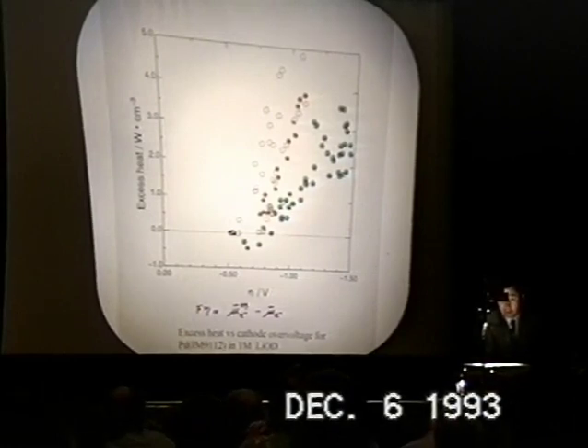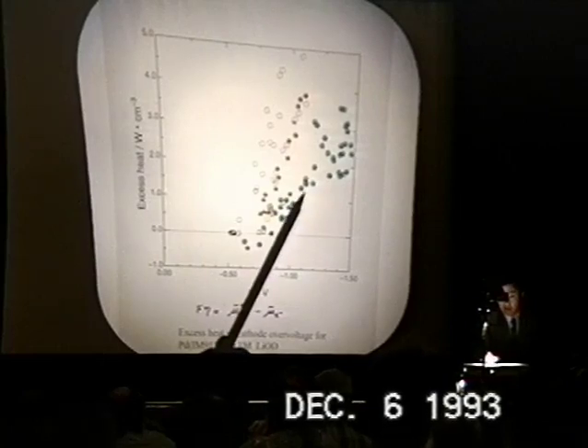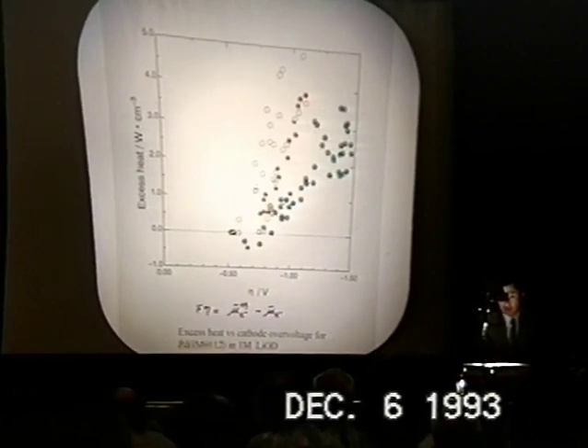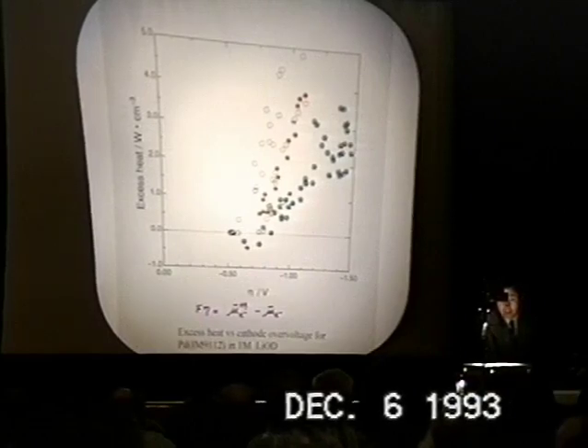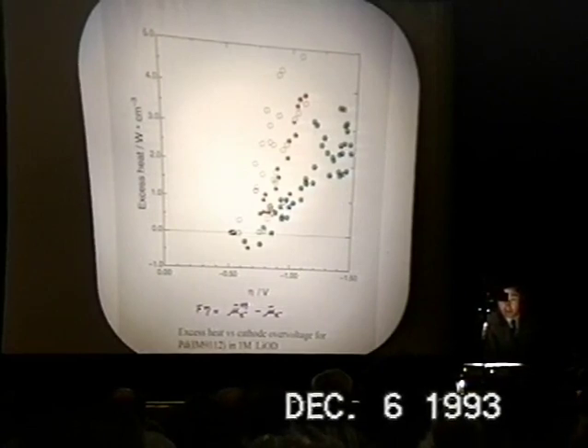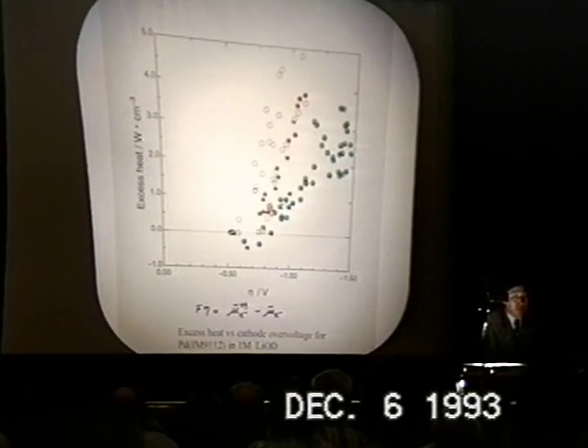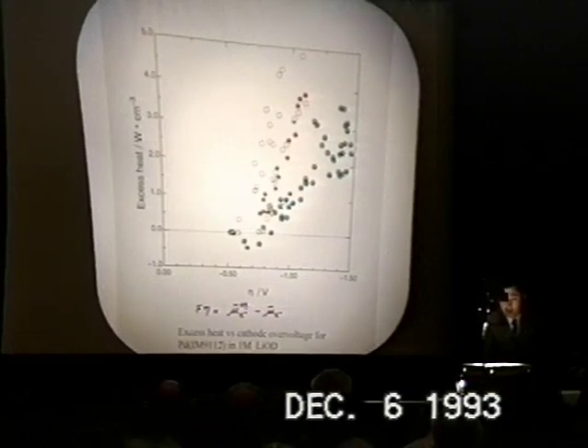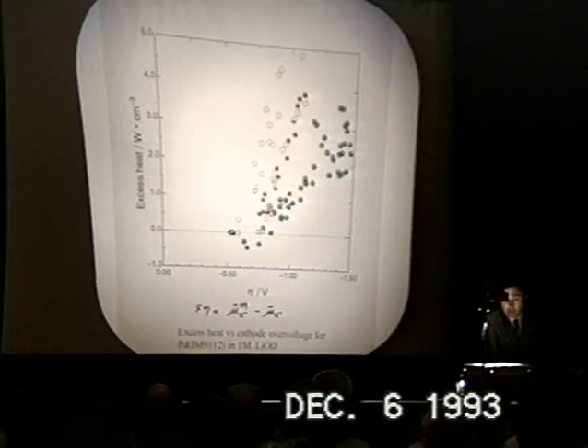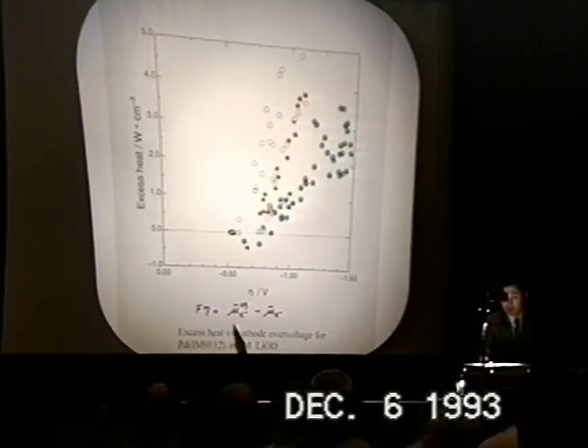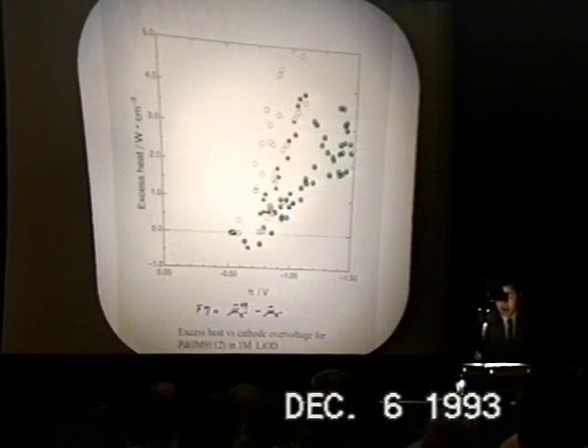But if we look at those data closely, those green data and red one and white one are well separated, and it looks as if they are well on the straight lines. The reason why we thought about plotting the data as a function of overvoltage is as a function of current density. The current density has nothing to do with the performance of the actual characteristics of palladium cathode. Only cathode overvoltage can give us the potential drop across the palladium solution interface, and also, as I have written down, we know the change of electrochemical potentials of electrons in the palladium cathode.